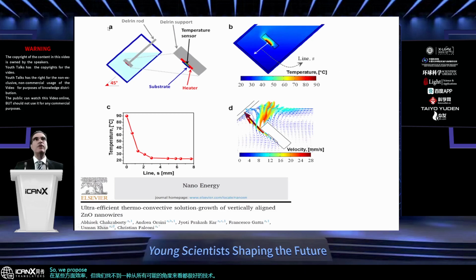So we propose that we can just take advantage of a heater that is placed in good thermal contact with the substrate. And in this way, we can have convective flows that can be strong enough. You see here the FEM simulation and also eye inspection reveal that the velocity can be easily up to 2 centimeters per second in proximity of the substrate. And this convective flow helps to continuously mix the solution, and also to improve the growth of the nanowires without any seed layer. In addition, we don't have lots of reaction far from the substrate because the rest of the solution is kept at just room temperature.